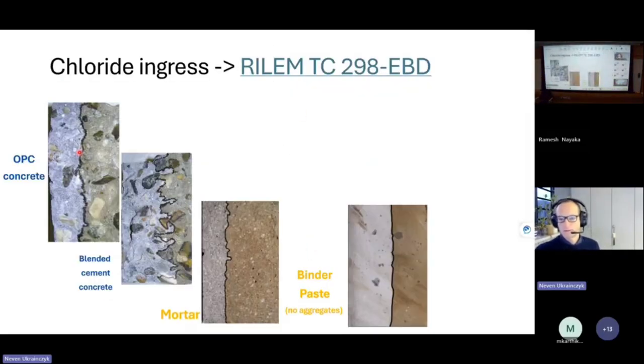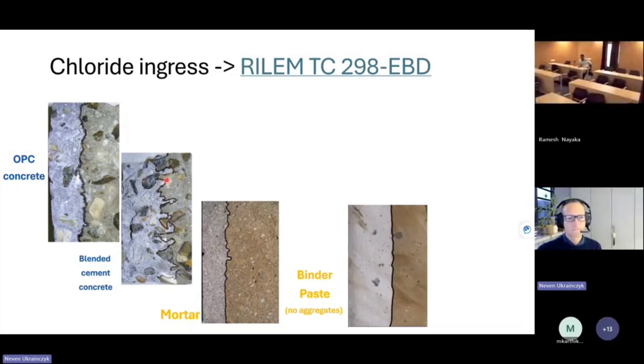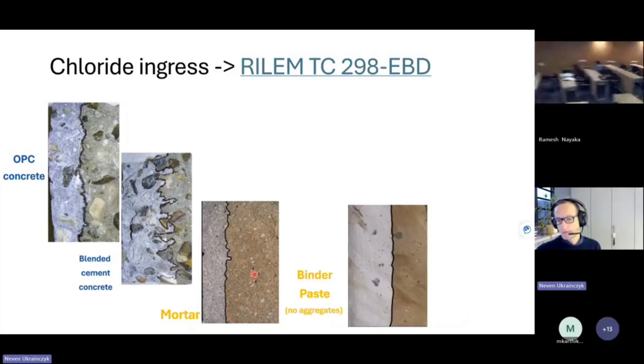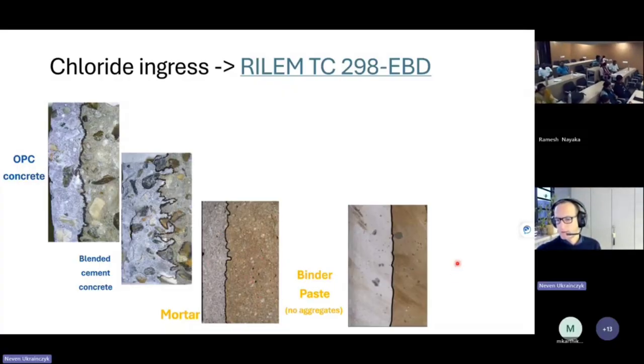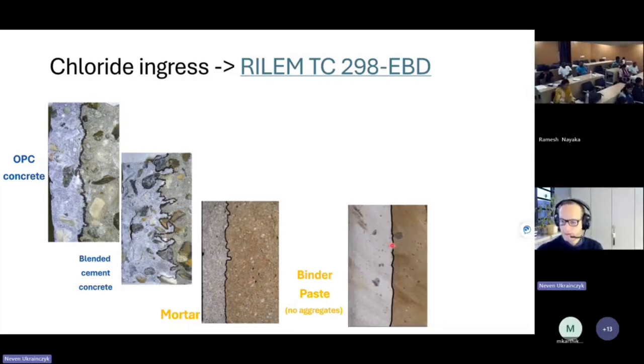And also different methods. So this is, if you have concrete, this is how it would look in the mortar. But this is the mortar, sorry. But this is the blended cement concrete. This is what I was telling you. This is ordinary Portland cement, and if you have the slag, here you can see how really these ITZs around the aggregates basically determine the critical path, because that's the porous region. And here now we also have mortar. It's also UHPC, basically. If you have very small aggregate, this would be like a UHPC, and you have binder paste without aggregates.